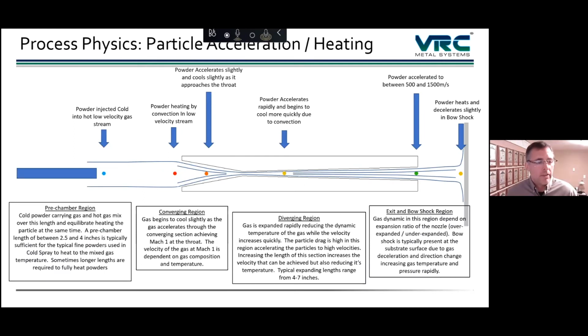So where all this acceleration is occurring is really in the nozzle. The rest of the system is a way to get the gases at the conditions we want them and the powders at the condition we want them to this nozzle. The nozzle is a converging, diverging nozzle, but just before the nozzle is where the powder is injected. So at that point, the gas is still hot, relatively speaking, and the powders do warm. So there is a component of warming that material that could either be good or bad.